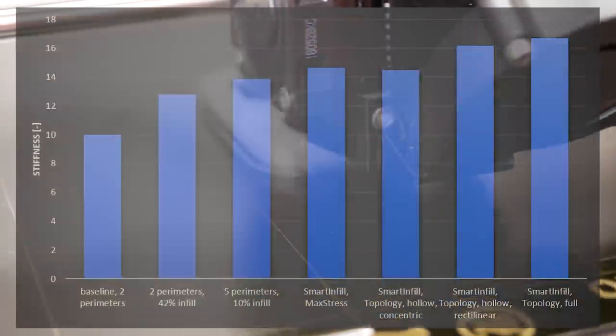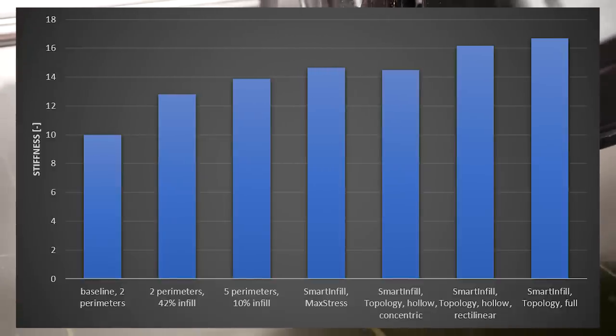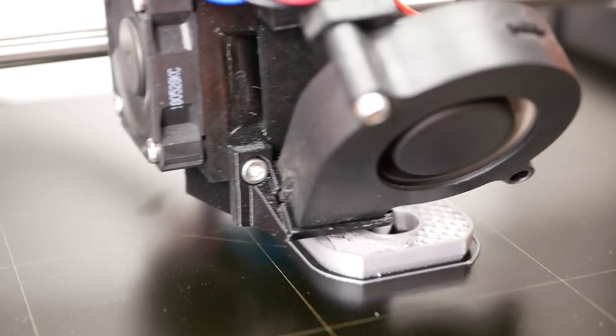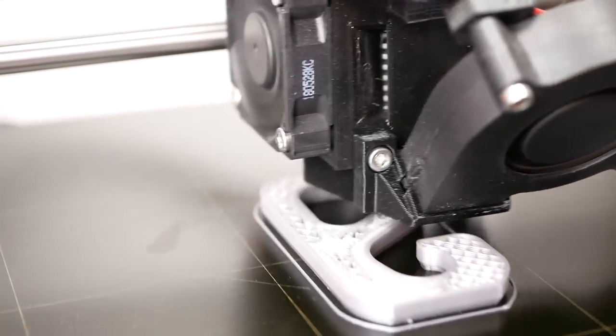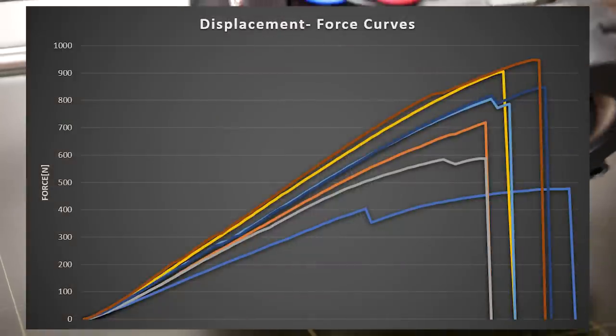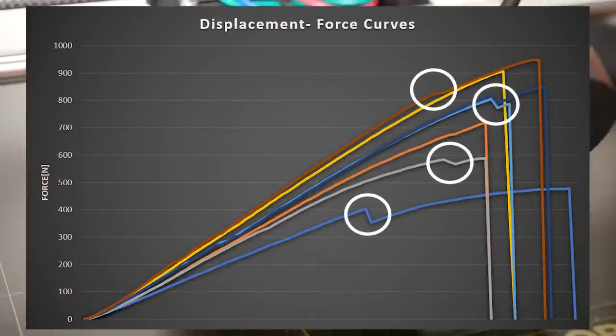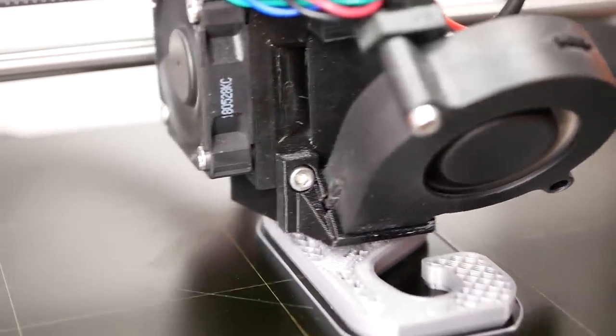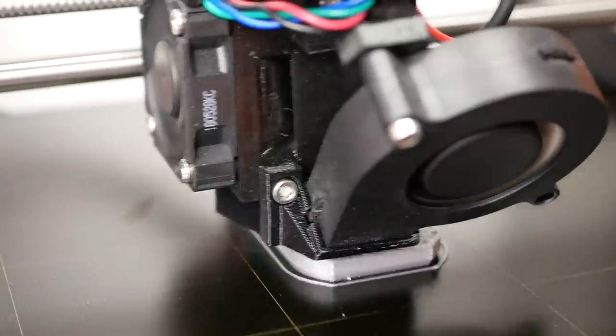The stiffness behaved kind of similarly, where again the topology-optimized parts were the best. Another interesting thing I observed is that the infill of the parts gradually failed during the test procedure. This can be seen when the displacement-force curves are interrupted. I'm not 100% sure if this is a good or bad thing. On one hand, it shows the part is kind of inhomogeneous; on the other hand, this could be a failsafe mechanism releasing high internal stresses before the whole part fails. What do you guys think?